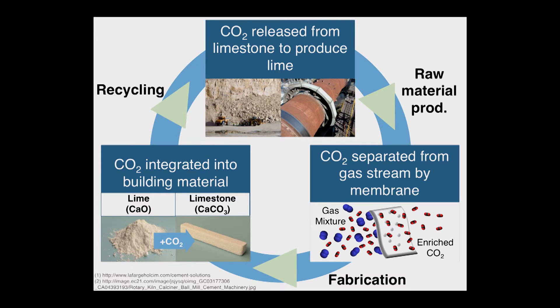This increases its strength and also sequesters our CO2. We designed these pieces to be reusable, rapidly assemblable building elements, which can be disassembled to be reused later. But when their lifetime is finally over, we can recycle them by heating them again to produce lime and CO2, and then repeat the cycle without quarrying any more limestone.